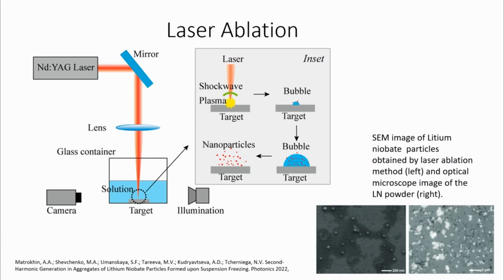Also for this process, a wealth of literature exists. However, it is possible to extract a few characteristic design features. In the laser ablation process, an intense laser beam is focused onto the surface of a target like this. The target may be a pure metal or oxide or even a mixed system. Because of the high energy input coming from a pulsed laser, the material of the target is vaporized instantaneously. This process preserves even the stoichiometry of a complex mixed target in the vapor phase.